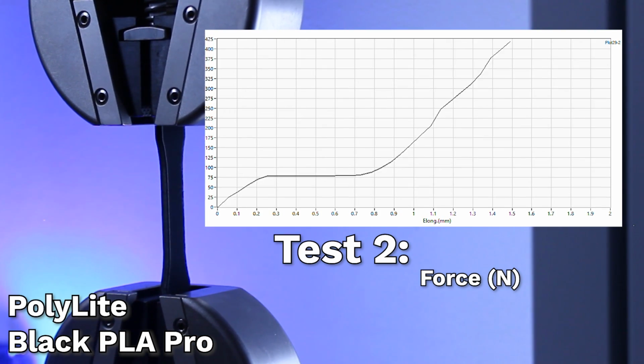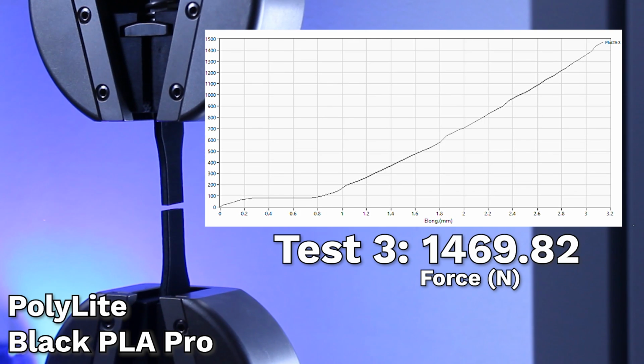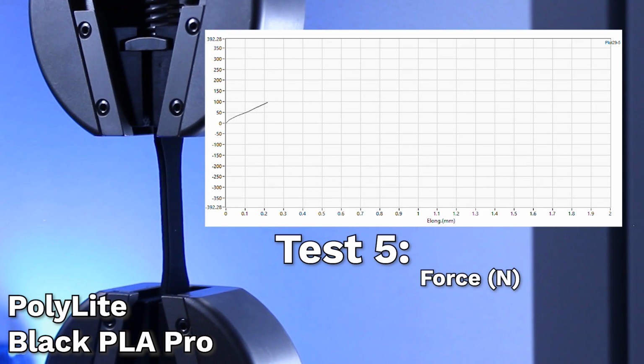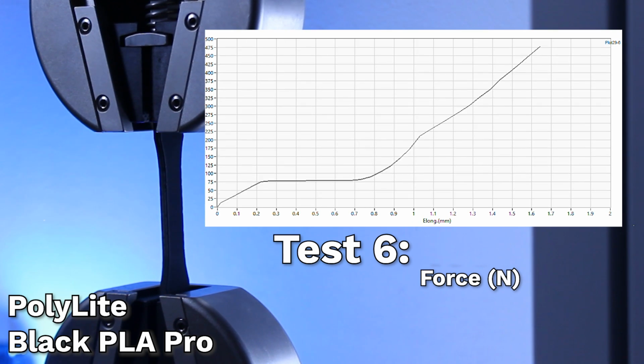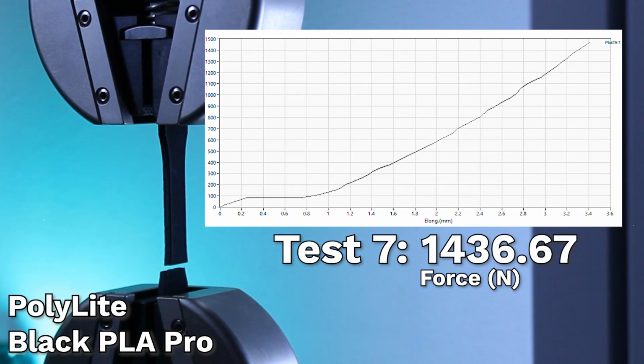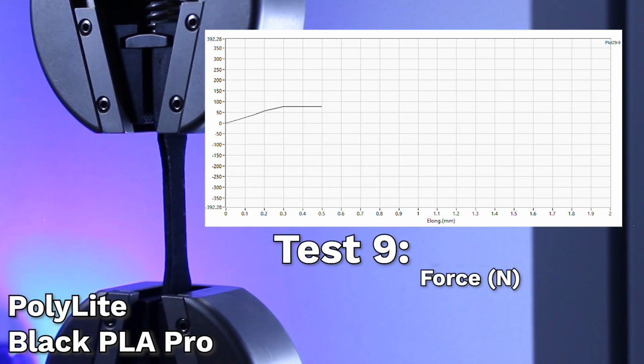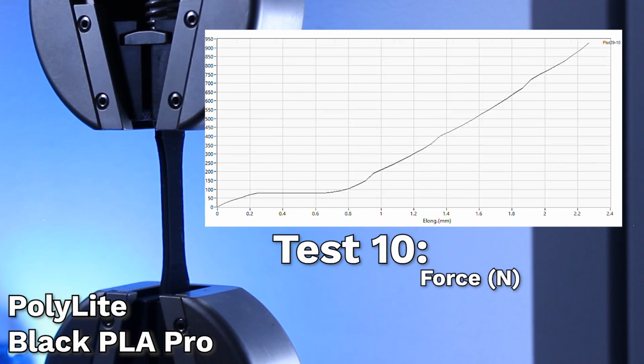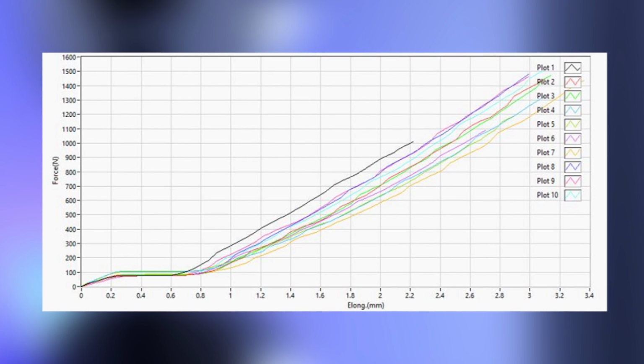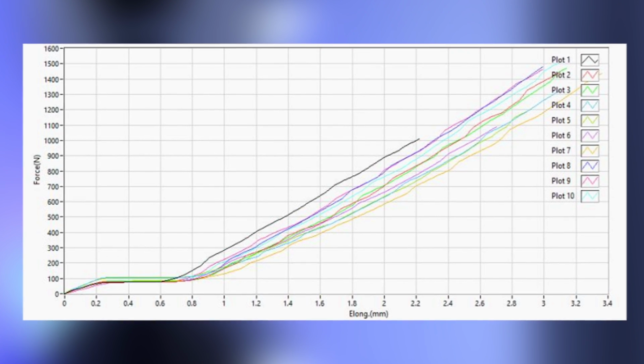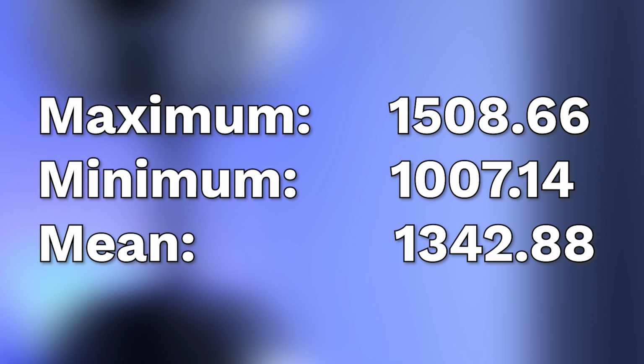Finally, our last test is Polymaker Polylite PLA. Again, it is standard PLA. We would expect it to be about the same as regular PLA. Once we pop these few tests, we come out with a mean force of 1342 newtons and a stress of about 26. This is lower. This is demonstrably lower. The Polylite PLA, again, very likely has additives in it.